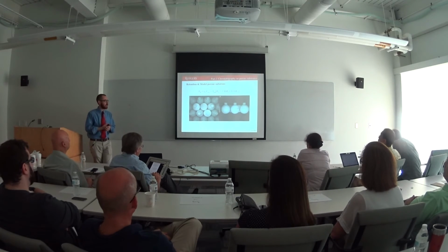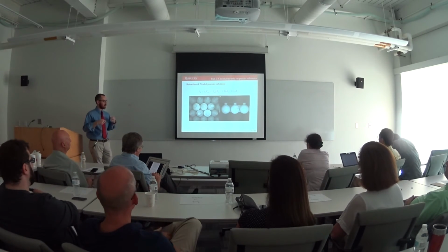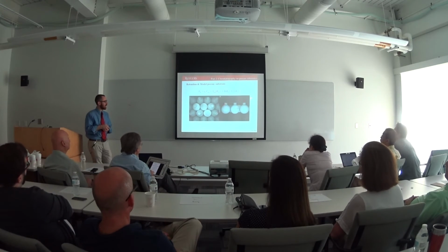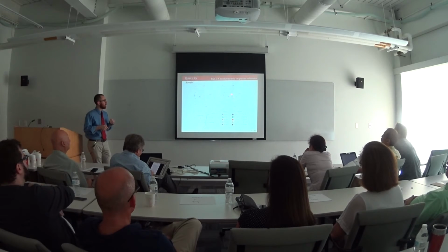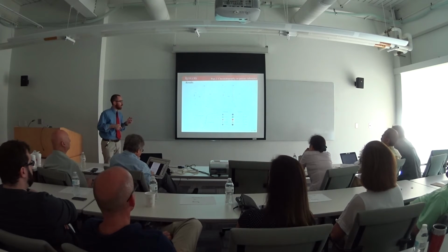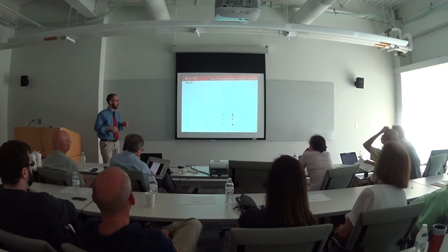I next took this information and employed a simple model substrate, which is shown here, on which to calculate retention volumes. Here we have our pores that are connected by these little cylindrical necks to a flat surface, and we have adsorption both on the surface and in the pores. Using that retention model, I was able to compare the retention of a simple series of linear polystyrenes on a porous column in all three adsorption regimes and showed critical retention.